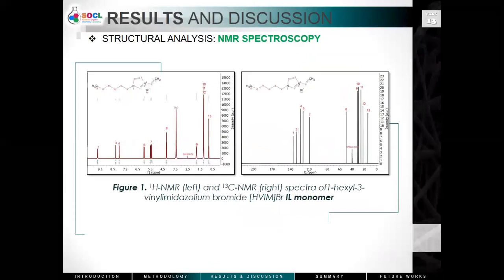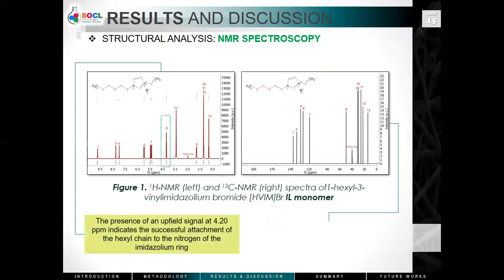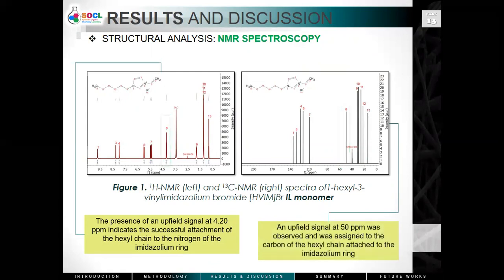For the results, the proton NMR spectrum is shown. Here, the presence of a signal at 4.20 ppm indicates a successful attachment of the hexyl chain to the nitrogen of the imidazolium ring. This is because of the formation of a quaternary ammonium salt from the reaction of N-vinyl imidazole and the 1-bromohexane. This was further validated by the carbon NMR spectrum in which an upfield signal at 50 ppm was observed and was assigned to the carbon of the hexyl chain attached to the imidazolium ring. The presence of downfield signals at 124 ppm, 130, and 136 ppm were due to the aromatic carbons of the imidazolium ring.